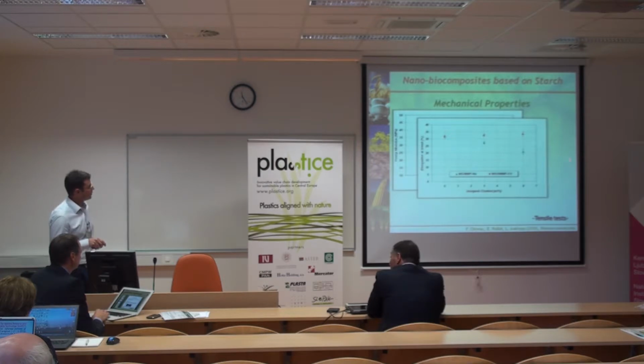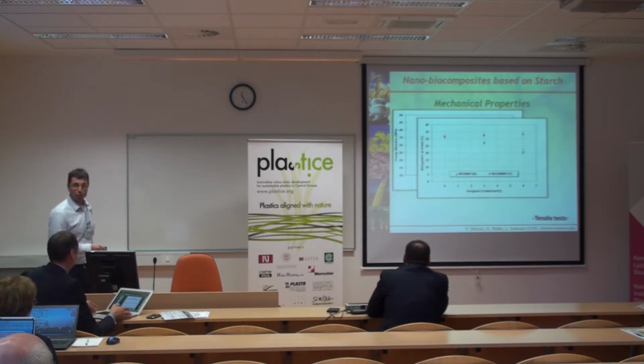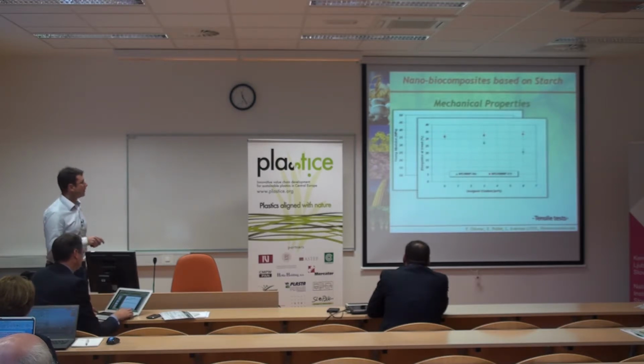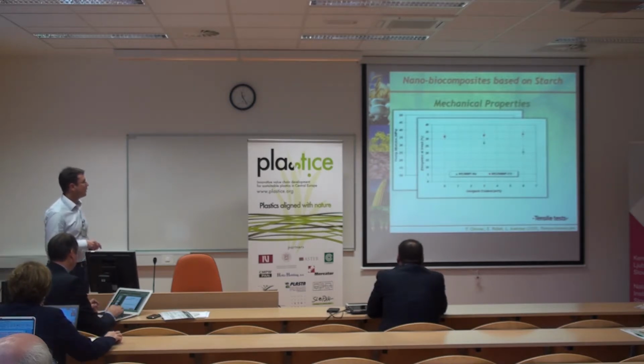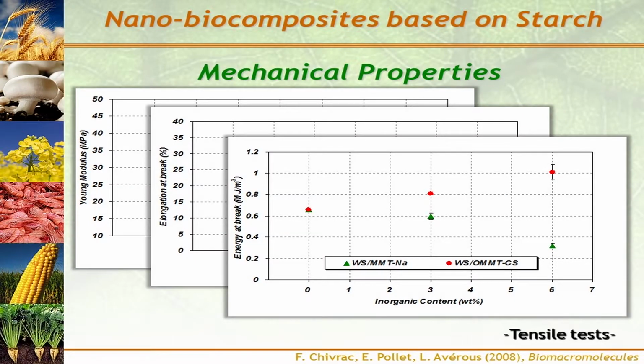You see that this is typical when you add the filler, you increase the modulus, but you may also decrease the elongation at break, which is the case with the unmodified clay because of the poor dispersion of the clay inside the matrix. Whereas when using the organomodified clay, which is exfoliated, you have a better dispersion and you maintain more or less the same value of elongation at break, which is quite interesting because the total energy at break increases and is much higher for the organomodified clay compared to the unmodified one.